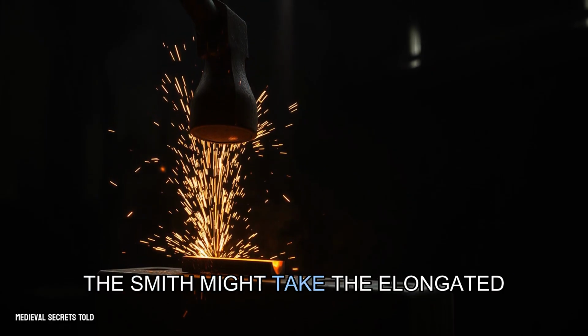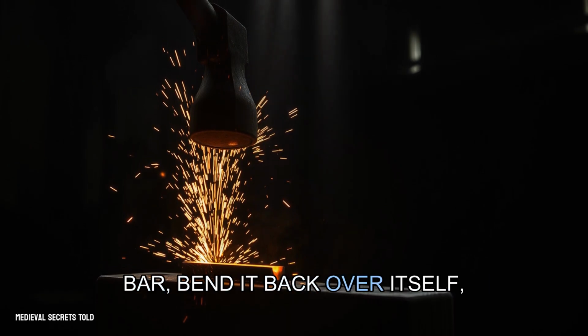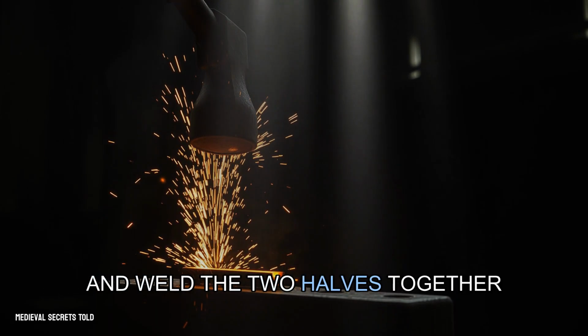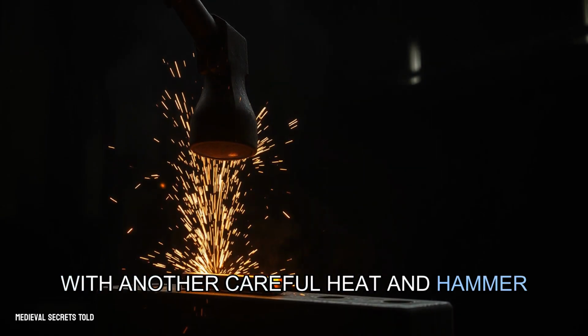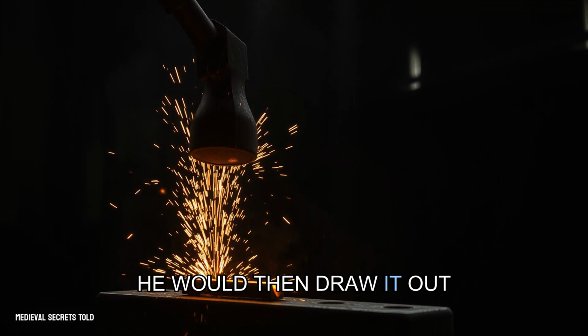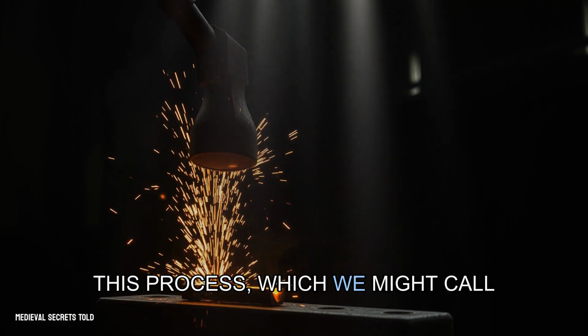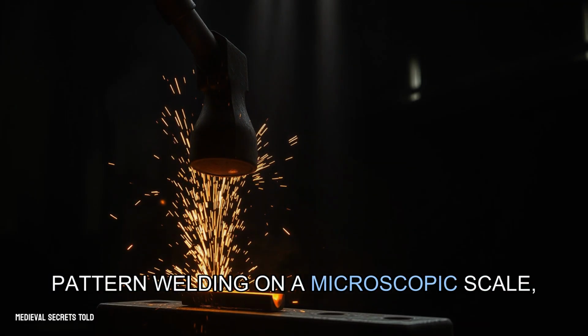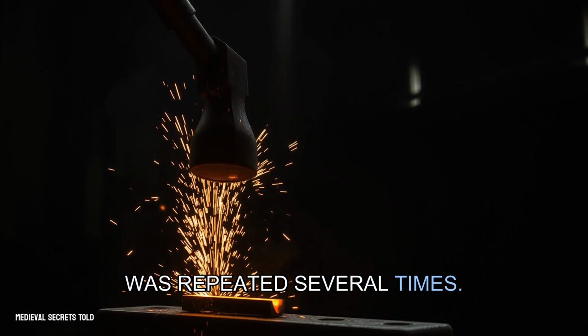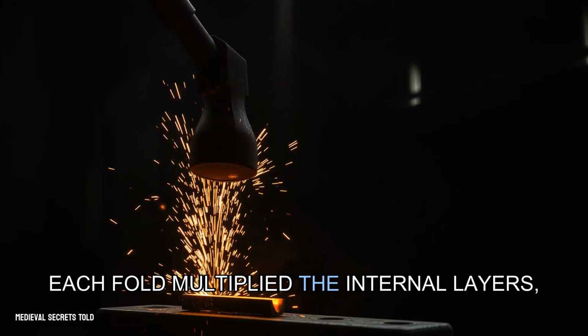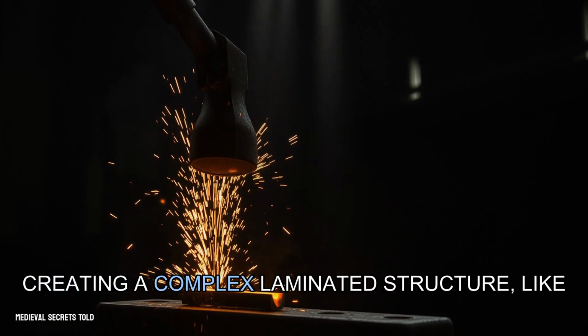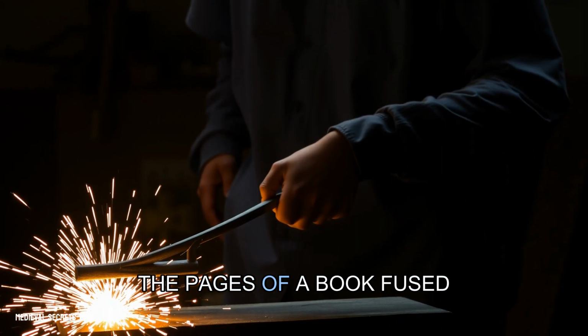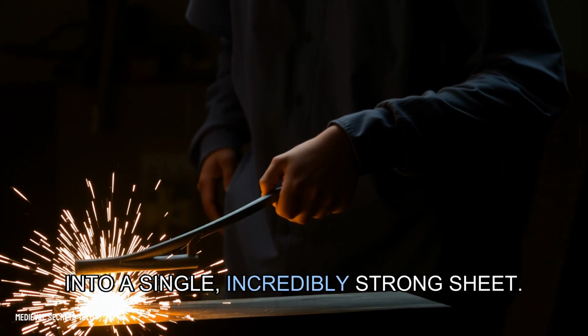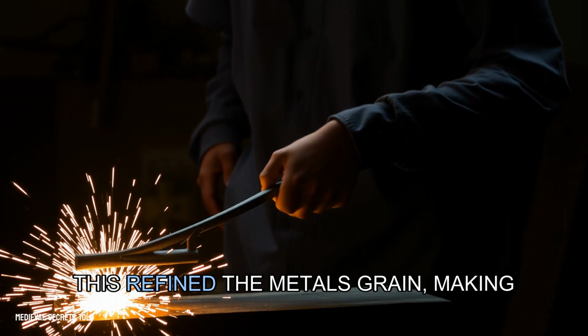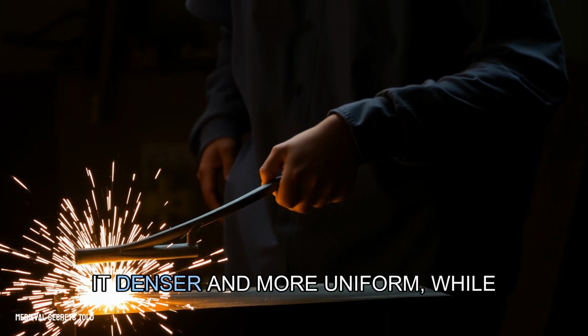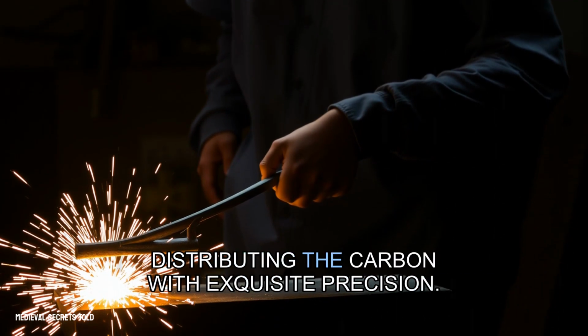Now came the transformative act of folding. The smith might take the elongated bar, bend it back over itself, and weld the two halves together with another careful heat and hammer blow. He would then draw it out once more. This process, which we might call pattern welding on a microscopic scale, was repeated several times. Each fold multiplied the internal layers, creating a complex laminated structure, like the pages of a book fused into a single, incredibly strong sheet. This refined the metal's grain, making it denser and more uniform, while distributing the carbon with exquisite precision.